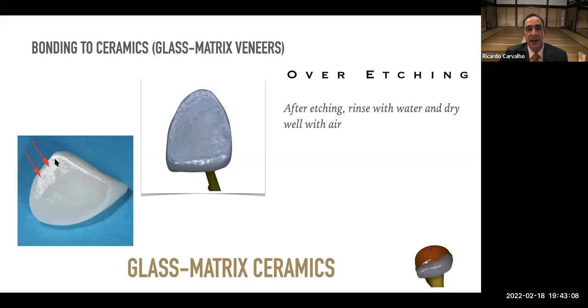And what you see here actually is a layer of residues of salt formation because the hydrofluoric acid reacted with the ceramic surface and formed some salts. These are particles that are loosely bound to the ceramic surface, and therefore they must be removed before we actually apply the silane or the bonding, because otherwise we will compromise the adhesion to the ceramic.